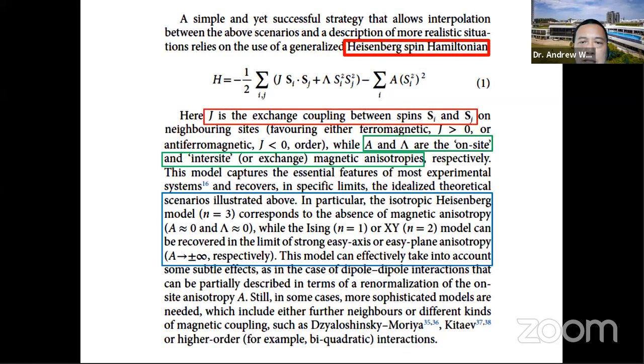The key thing is that in the Ising or XY model, you can get the case where A and lambda here are non-zero. So you have to take these two terms into account for those models. I'm going to talk quite a bit on anisotropy in my next few slides, in the papers that we did, because we believe it explains the origin of magnetism in many of these 2D systems.